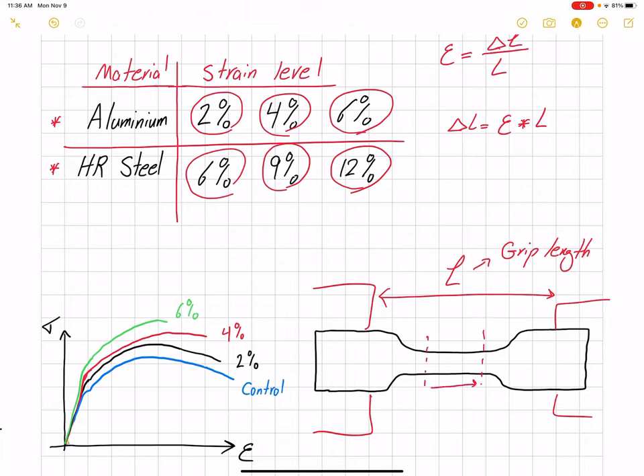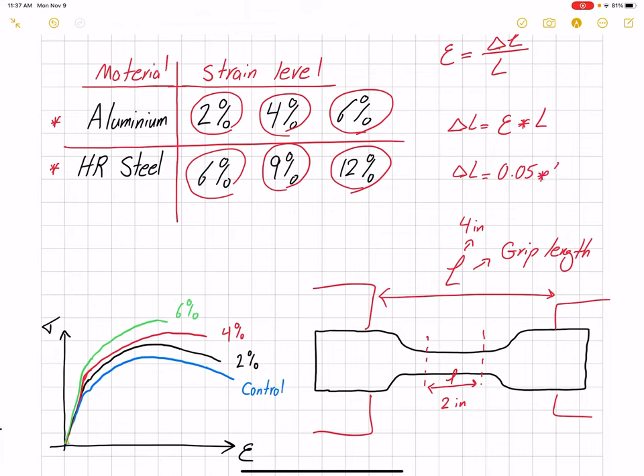The strain hardening is being applied across the entire grip length. This should not be confused with the gauge length, which I'll denote with a small 'l' — used for determining the elongation of our material or area reduction. Our gauge length is usually two inches; the grip length could be different depending on how you place the specimens, but let's say it's four inches. If you're going to apply, say, five percent strain, you will have 0.2 inch displacement.